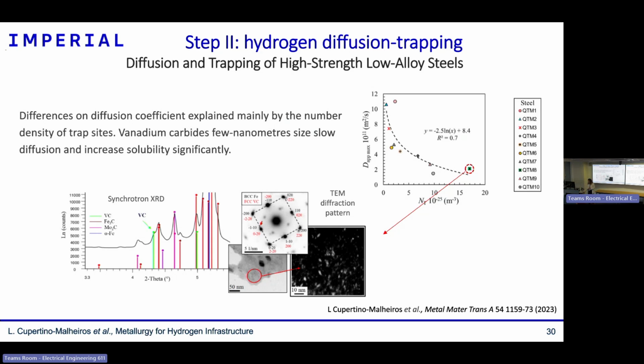The second point, no, it's not only vanadium carbides, it's any structural feature that traps hydrogen. And now you need to look at how many you have in a structure, what's the binding energy. But in principle, lots of other second phase particles and also lots of other types of crystal defects can slow down diffusion kinetics. The question is, can they prevent hydrogen embrittlement? And that's a much more difficult one.